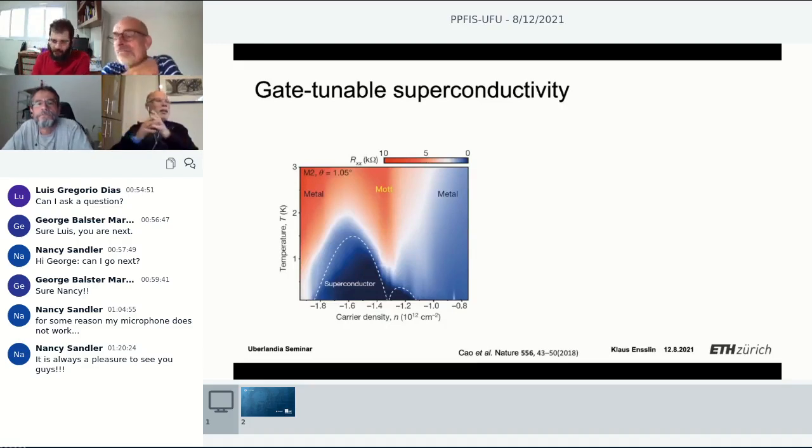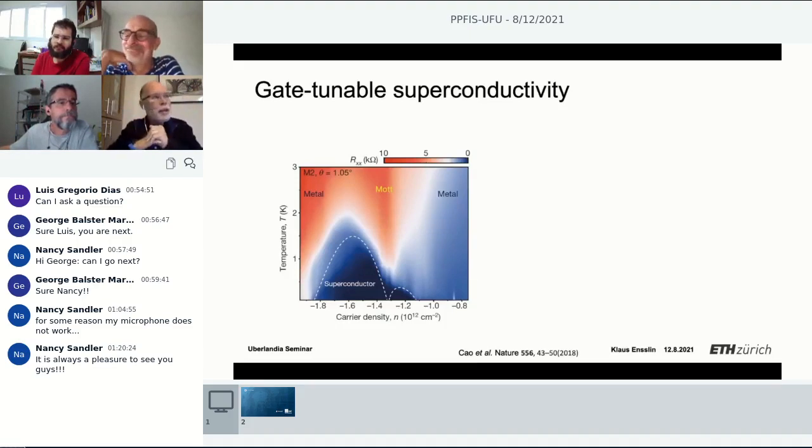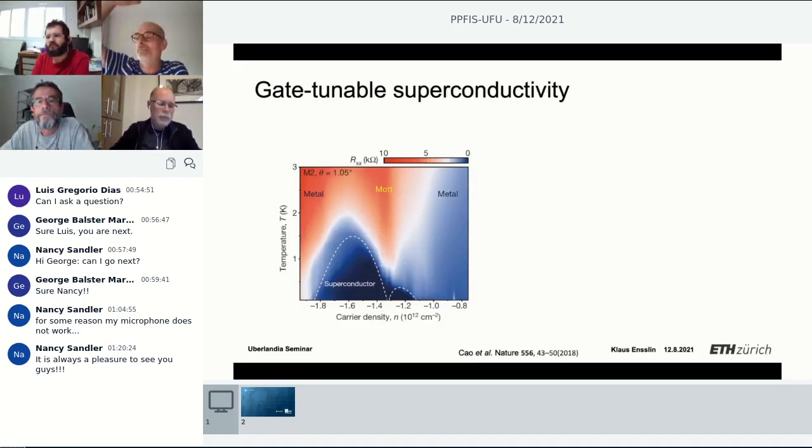And while we're at this, when you vary the Fermi energy, scanning through the wine bottle profile or the Mexican hat profile, do you actually measure the Shubnikov-de Haas in this regime? And can you actually see the electron and hole orbits, the different types that happen in this regime? Yes, absolutely. And there's a Lifshitz transition, because the topology of the Fermi surface changes as you go through the maximum. If you're on top of the maximum, it's a simple circle. Once you go below the maximum, then you have a hole in the center. And that gives directly rise to different degeneracies in Shubnikov-de Haas.